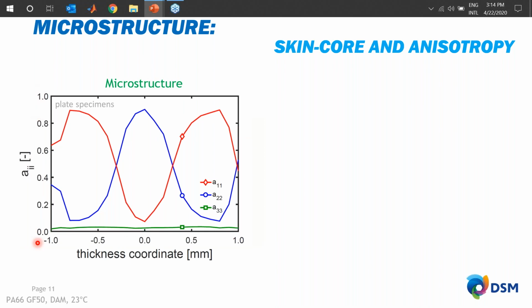As a result, you get a very pronounced glass fiber orientation, as you can see over here on the left. So you plot the A values, so basically the values of the orientation tensor, where A11 is the orientation in the flow direction, A22 the orientation perpendicular to the flow direction, and A33 the orientation out of plane. Then you can see that in the 2D plane, so basically in the plane of the plate, you have a very pronounced skin core morphology because of the edges. So on the outside, you see that you have highly oriented fibers, and in the middle you have perpendicularly oriented fibers, and of course it's symmetric because you have the edges on the other side.